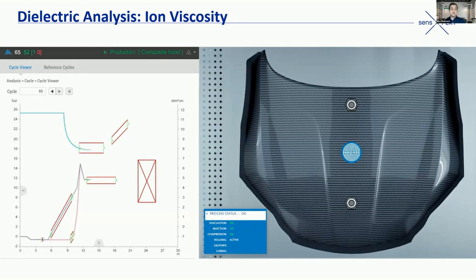And really these gates that we put here, these red lines, are really just process gates. So you as a process engineer can decide this is what an acceptable part quality looks like, right? All of these, the pressure transducer should follow this pattern. The dielectric sensor should reach this minimum viscosity and start to cure at this time. So we can see all that and track that in real time during the process. And this was really the origin of this whole solution. And then we decided, let's take it one step further.